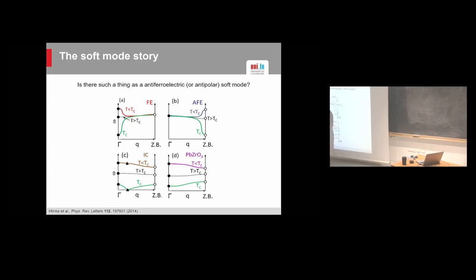So this sketch A describes what you would expect for a ferroelectric phase transition. So you have above, where is above TC? You have here. So when you go to TC towards the transition, the idea is that this phonon frequency goes down until it's unstable and then it goes up again. But the one at the zone boundary doesn't really feel it.